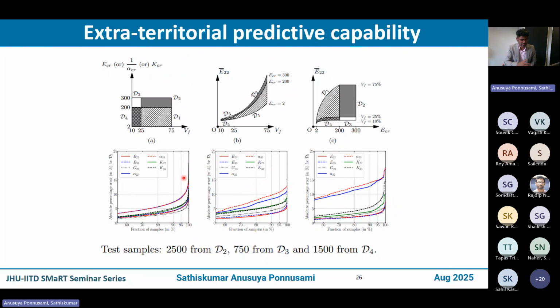And what we really observed is, again, more than 90% of the samples in the extrapolated or extraterritorial regions still provided a reasonable prediction for the properties, as you see here, for all sorts of properties that you can think of, both mechanical but also thermomechanical properties. Which is good news, because the model is now not only generalized for arbitrary material properties and material combinations, but also it can extrapolate well in the neighboring domains outside its training space.